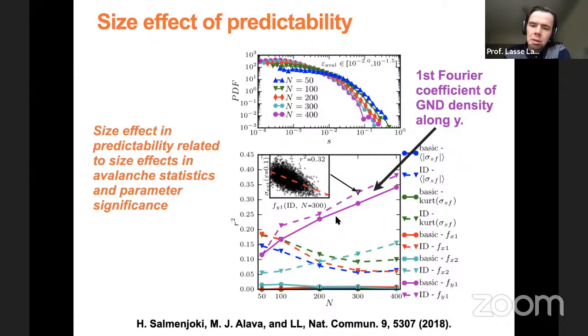So you see that some of these features also exhibit size dependence. For instance, there is this one feature that is especially important, which is the first Fourier coefficient of the geometrically necessary dislocation density along y, which is the direction perpendicular to the dislocation motion. This tells you if there's some imbalance in the y direction of the positive and negative dislocations, and this seems to be an informative predictor, or descriptor of the initial state, which also exhibits a size effect like this. So it becomes more important for larger systems. That maybe explains a little bit why there's the size effect.